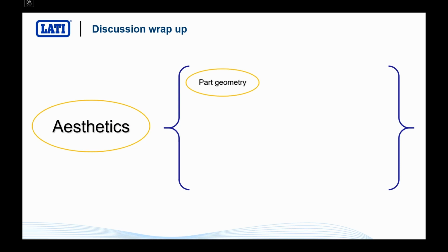First of all, the part geometry. The thickness of the walls will play a major role in the quality of your part. Low thicknesses promote high shear stress, high temperature, so they can look much more glossy, but they can also promote material degradation. High thicknesses will promote sink marks, and you will have a slowing in the melt diffusion during the filling part, and this can create bad streaks on the surface. So the relevance of the part geometry is dramatic. You want to keep the thickness of your walls as homogeneous as possible in order to have more or less the same surface finish all over your part.